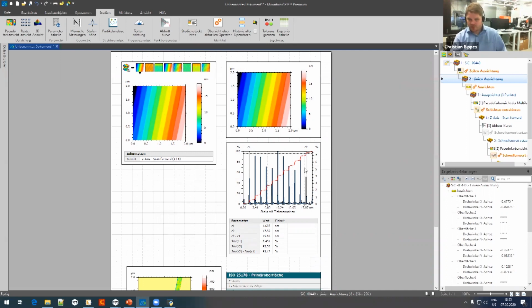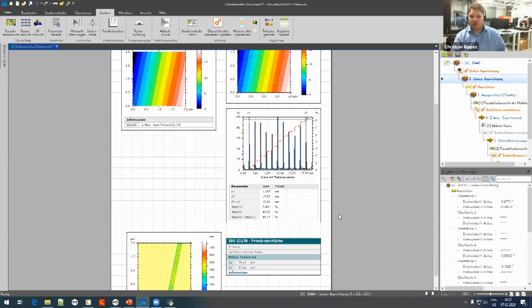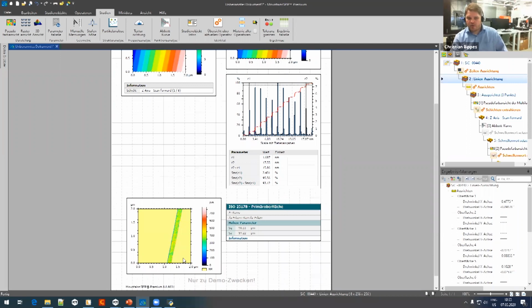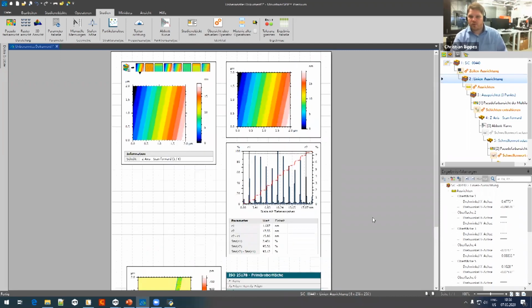And then if you measure these steps, here I think it's 10 steps that I measured, you end up with 1.5 nanometers per step. What you could also do in this software is extract the surface of a single terrace and apply a roughness measurement to this single plane, and then you would end up with something like 90 picometers for this surface, which is basically what the manufacturer of the sample also specifies as the surface roughness on these terraces.